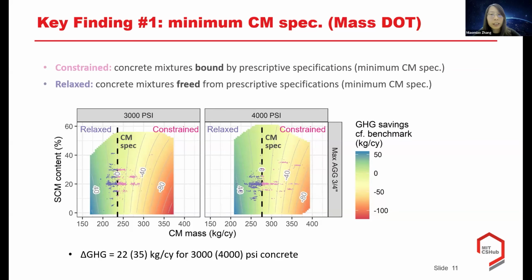We also investigate the actual GHG savings based on the operational data from ready-mix concrete mixtures. In these figures, the scatters are the concrete database we have. Based on the CM spec, we'll classify the concrete products into 2 groups, the relaxed group and the constrained group. We compared the GHG emissions between constrained and the relaxed group, and the average delta GHG is about 22 kg per cubic yard for 3,000 PSI concrete and 35 kg per cubic yard for 4,000 PSI concrete.